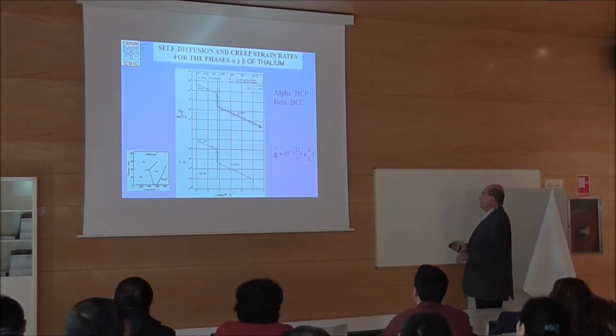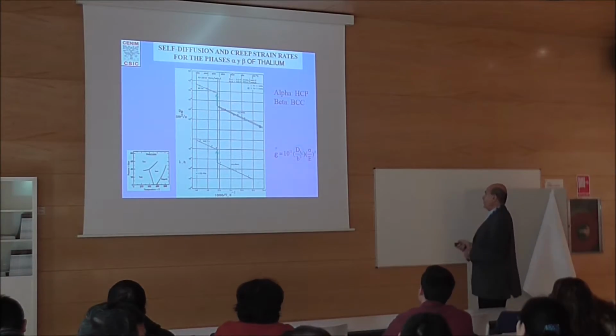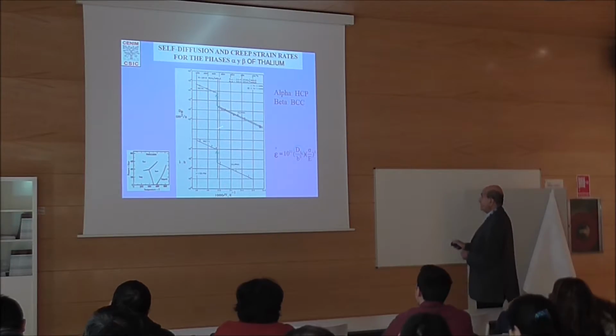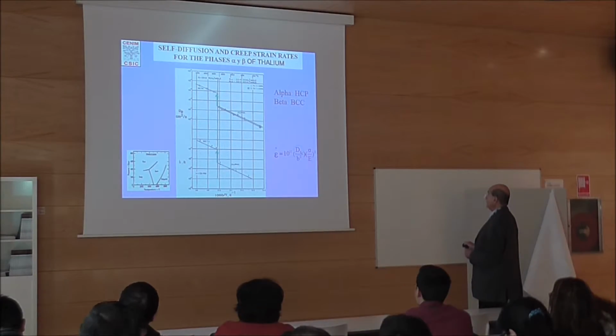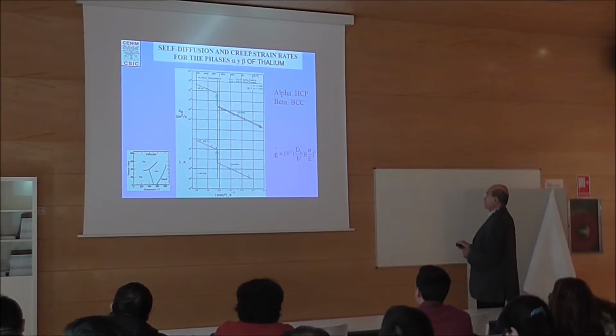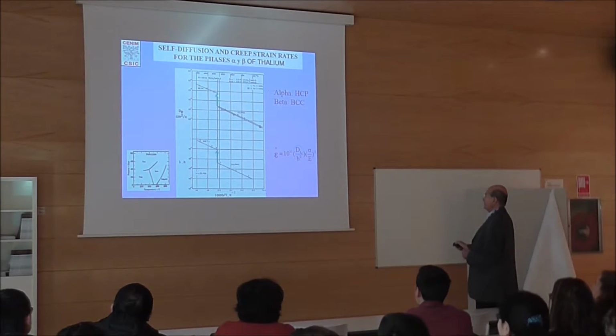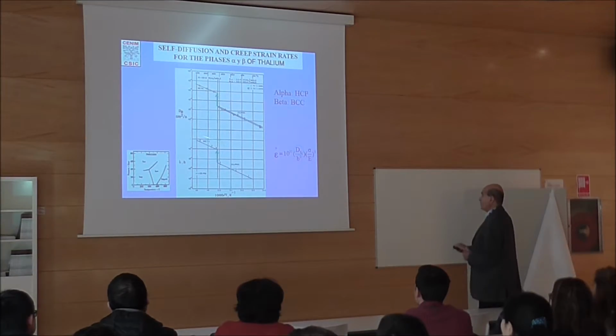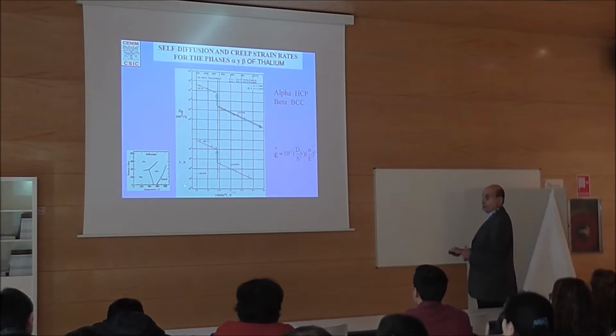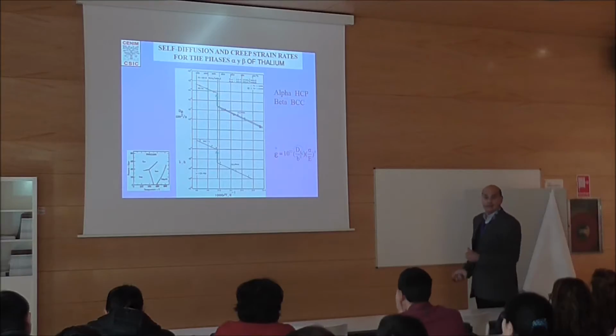Okay, if you don't like the iron example, you may also have thallium. Thallium is inverse. This is from the chemist, radiotracer data, and you have alpha. The alpha is a close-packed structure, so the diffusivity is low, and it changes as soon as you have the phase transformation. It goes to beta, an open structure, and it will increase. You may now do a creep test here, strain rate versus 1/T, which is proportional to the diffusivity. You have exactly the same thing.